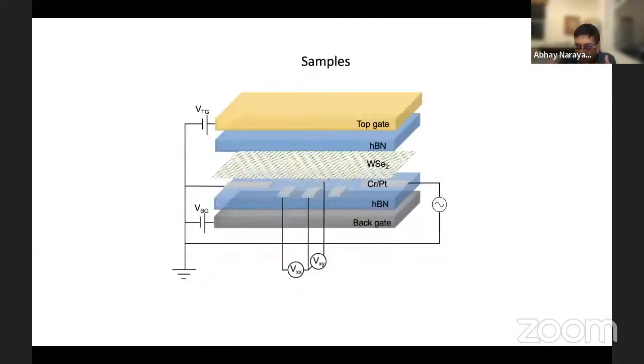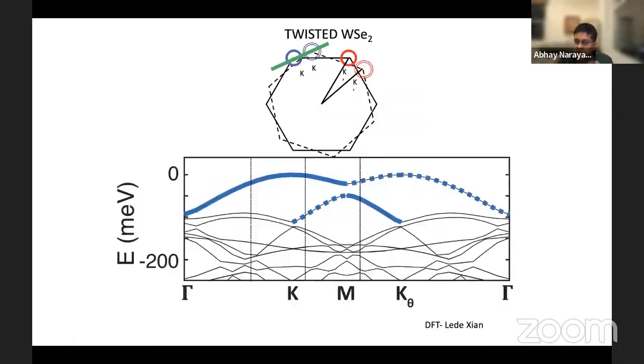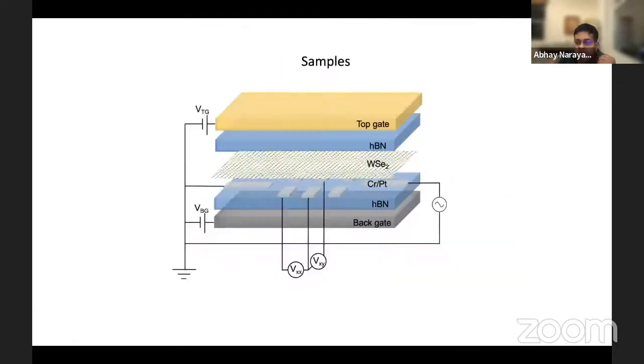Okay, so here's how the samples actually look, at least schematically. You have this bilayer of tungsten diselenide, and it has dielectrics on the top and bottom, hexagonal boron nitride. And then there are gate electrodes on the top and bottom. If you apply the same voltage to both of these electrodes relative to the tungsten diselenide, you can add charge to the tungsten diselenide capacitively. And if you apply equal and opposite voltages to the top and bottom, then you end up creating a pure electric field across this bilayer.